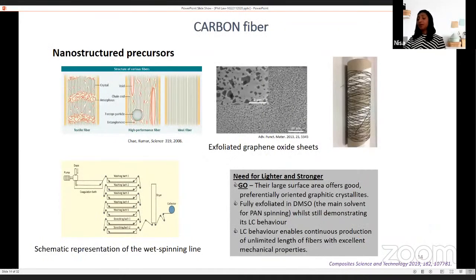So further in my research, our target was to make high performance fibers. An ideal fiber is one that will have very high strength, modulus, damage tolerance, and compressive properties. As you can see from the figure, the fiber will be free from all defects and impurities. Though carbon fibers are high strength materials, the mechanical strength of the current carbon fibers is limited by the presence of voids, defects, and impurities in their fiber structure. Theoretically, it is estimated that carbon fibers can be made 10 times stronger than currently available fibers.